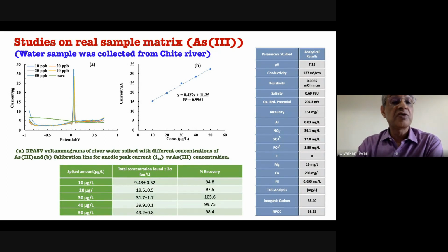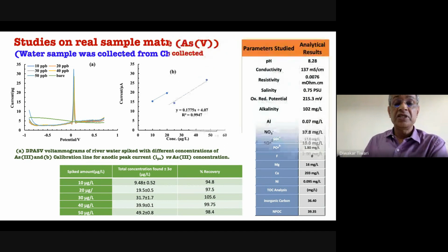We could obtain it for varying the concentration from 10 ppb to 40 ppb, 50 ppb. And this is on the right hand side the water quality that has been measured, and that has been shown here. Inorganic carbon, of course, of this water was very high. And the second thing is that those who are doing these kinds of studies must be knowing that the percentage of the recovery is an important quantity. So recovery, we could obtain it from 94 to 105%, which is very reasonable. And in most of the studies, if we are getting from more than 90% to 110%, this is a good recovery that we used to say.